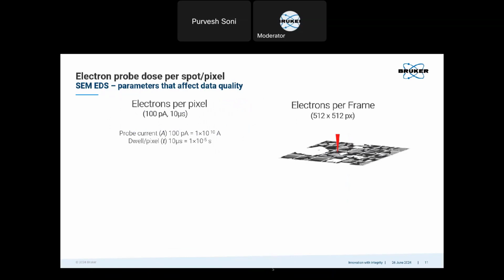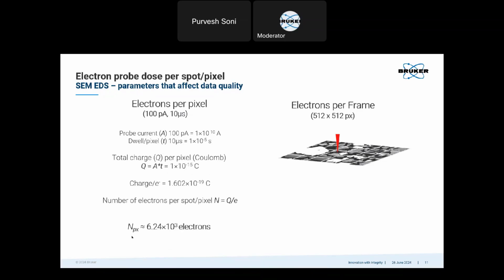So now let's take 100 picoampere and 10 microseconds as beam parameters, and calculate how many electrons are reaching the sample. The total charge for 100 picoamperes probe current and dwell time of 10 microseconds will be this multiplied with this, so 10 power minus 15 coulomb. If we divide this by the elementary charge, the charge of a single electron, then we get the total number of electrons, which is around 6,000 under these conditions. And now, if we have an image of 512 by 512 pixels, then we will have 1.63 billion electrons per frame.